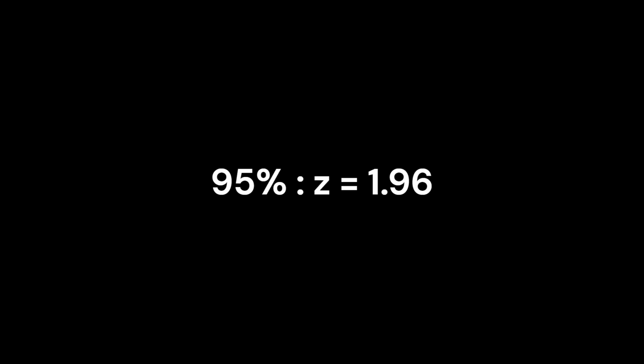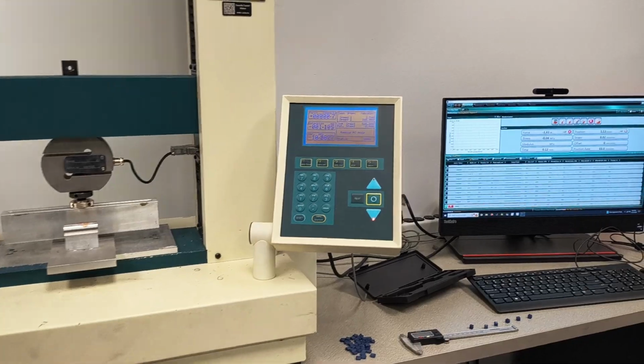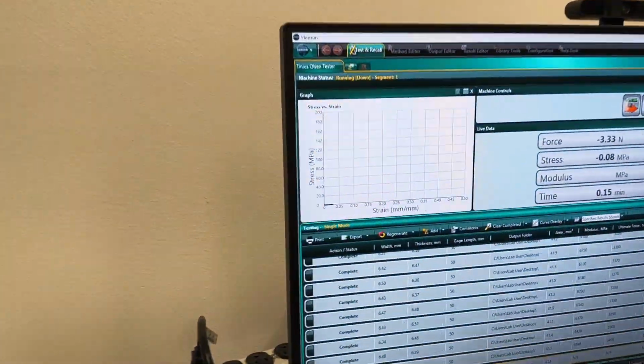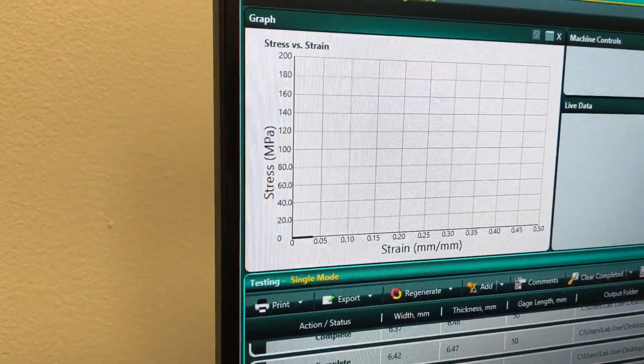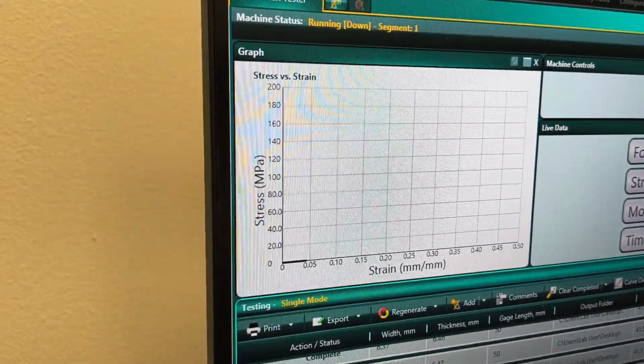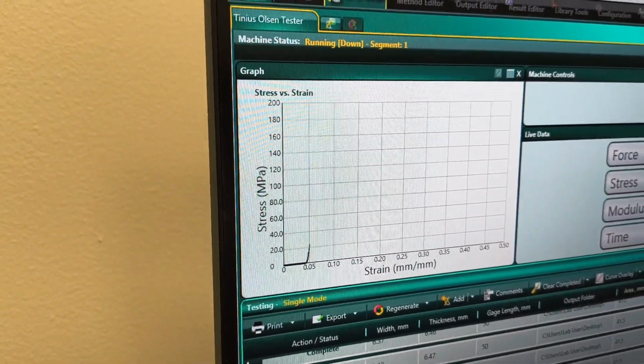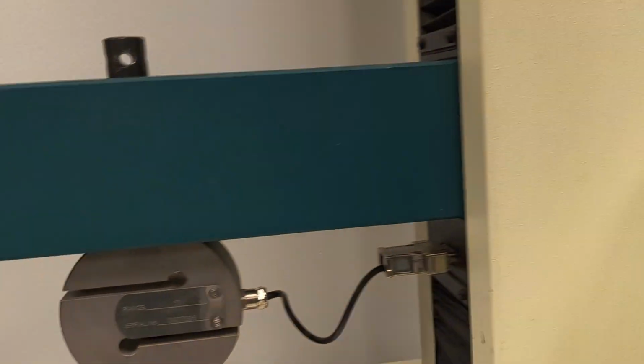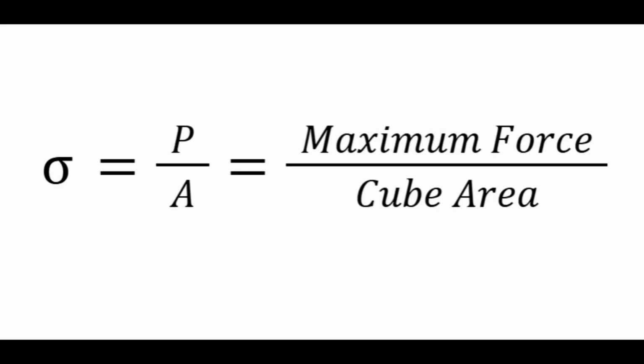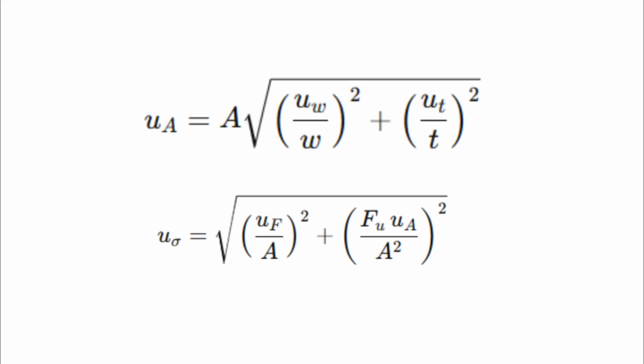Another benefit of these sample statistics is that a few error sources are subsequently included in our resulting data. The error source that is not included in the variation is the cross-sectional area of each cube, which is used to calculate the ultimate stress from the maximum force on each cube. When propagating the area variation through the stress equation, we find that the uncertainty increases by a noticeable but small amount, since the variation in the readings was higher than the caliper's precision.